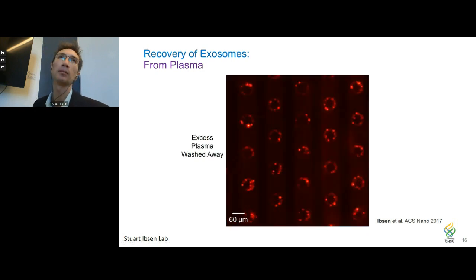So this is really exciting because the traditional method of being able to recover exosomes and other extracellular vesicles from plasma is an overnight ultracentrifugation. So that's like 16 hours of an ultracentrifuge use. And that's very difficult to be able to scale up for a clinical laboratory environment. Another way that people traditionally get exosomes out is through filtration techniques, but that can require a lot of starting material and is also very labor intensive. So this technique is really quite remarkable in being able to collect these particles in such a short period of time.